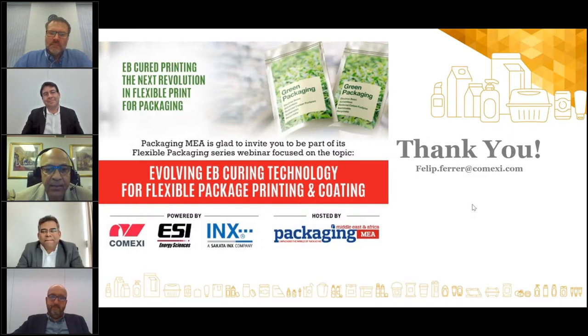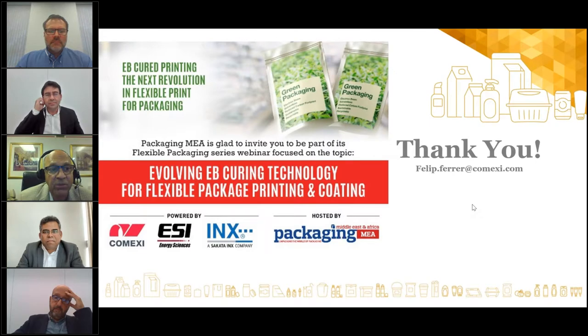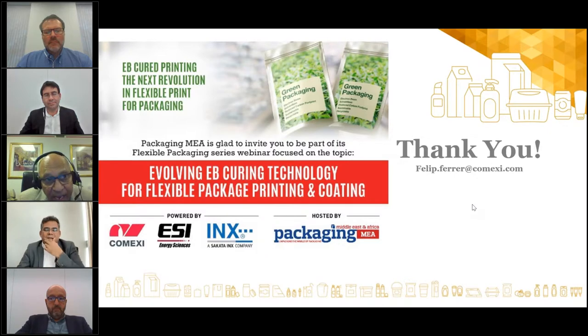Yeah, and unfortunately, I've done a lot of work with people mentioned EVOH. EVOH is used a lot as a barrier in coex films. And one of the big problems with EVOH is its moisture sensitivity. That means that at high humidity, in places like Spain or even the Boston area in July, you do get a lot of high humidity. And in that high humidity, the barrier does not function very well, specifically for EVOH. So one option is, can I cross-link the polyethylene and reduce the moisture sensitivity of EVOH? Unfortunately, we could not do that. And there are no current technologies, either using EB OPVs or cross-linking the film, to improve the barrier properties as required by flexible packaging.